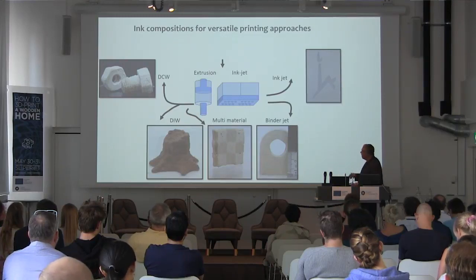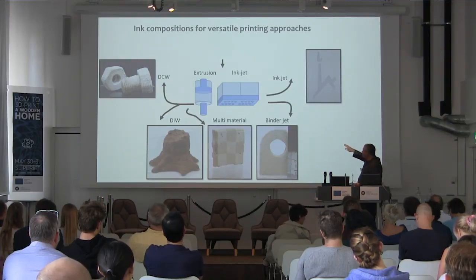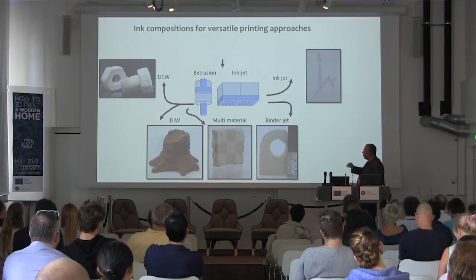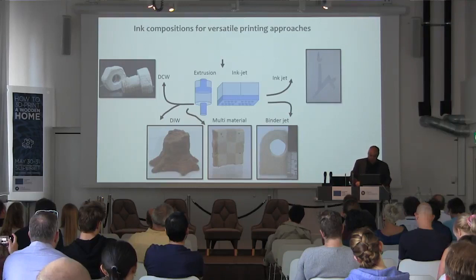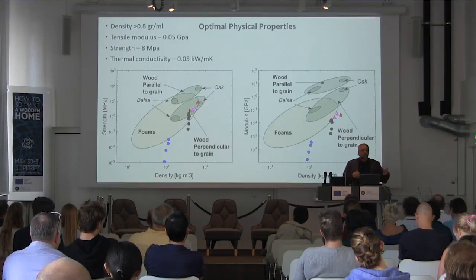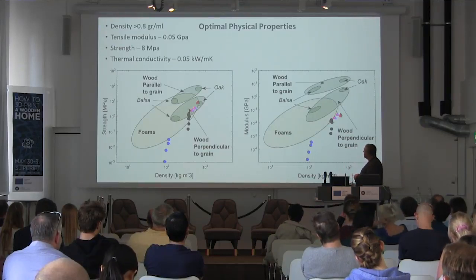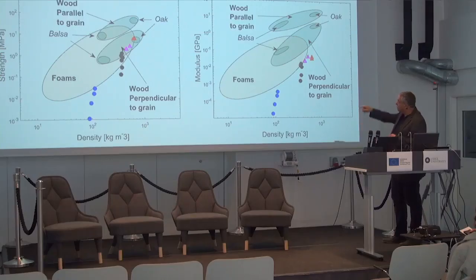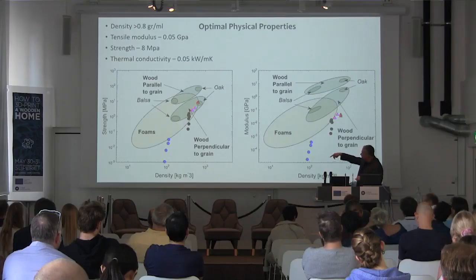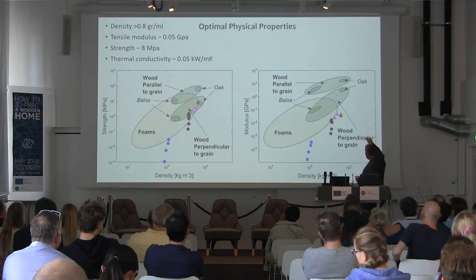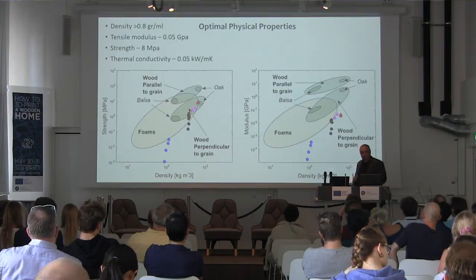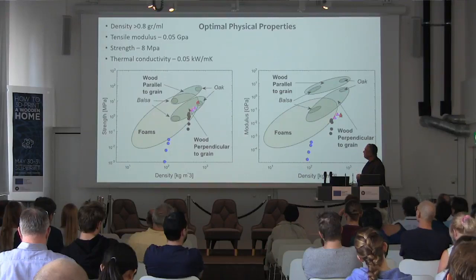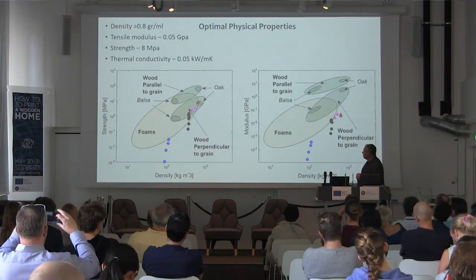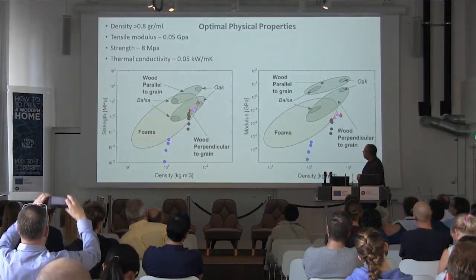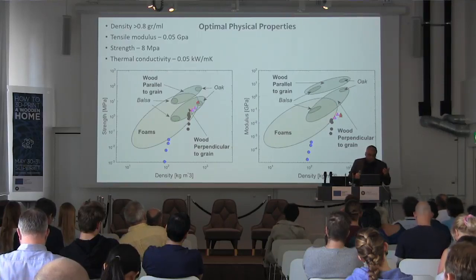So no synthetic materials. And we've been able to use it in inkjet printing, binder jet printers, and also extrusion, combining different materials, direct print, and so on. And the mechanical properties that you can achieve in some of these methods are quite significant. You can see here on the x-axis the modulus and the density, and here the density and the strength of foams or oak. And you can see that we can achieve quite strong materials where the optimal was a density of 0.8 gram per milliliter, tensile modulus of 0.05 gigapascal, strength of 8 megapascal, and thermal conductivity less than 0.05 kilowatt per meter Kelvin. So I think that we are really going in the right direction.